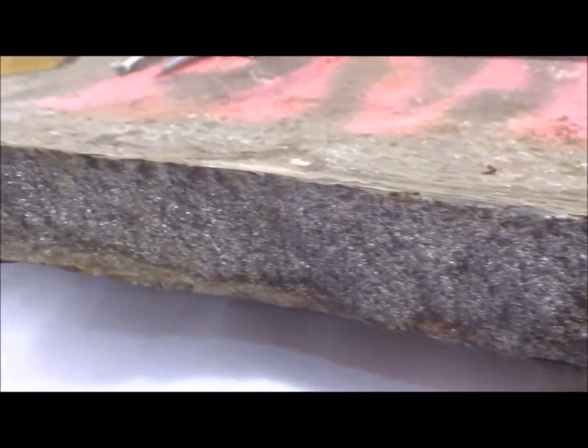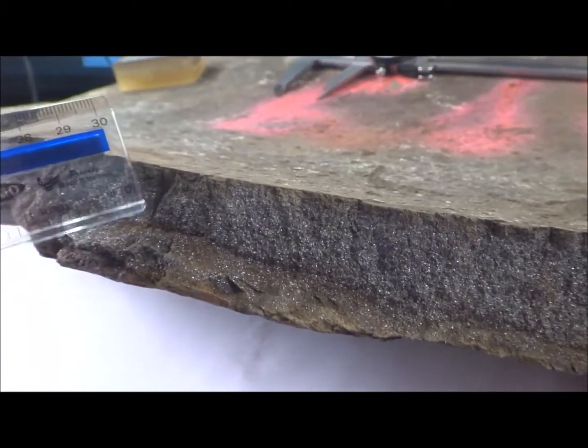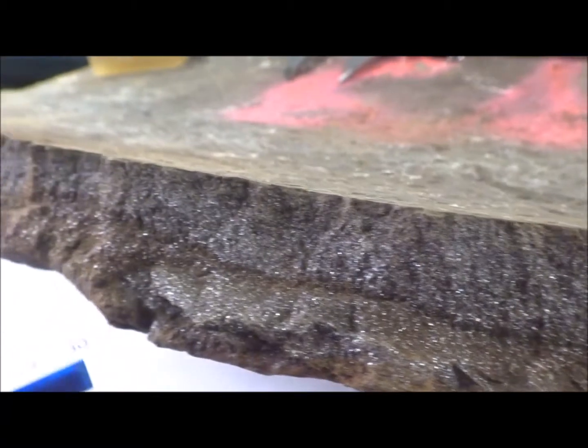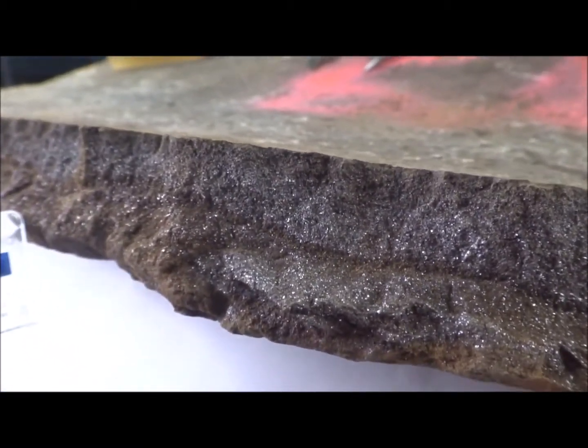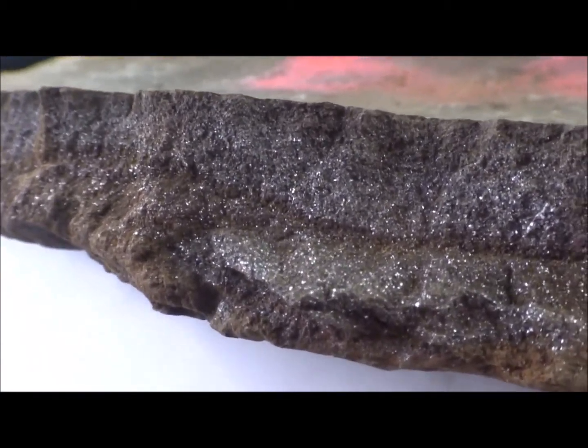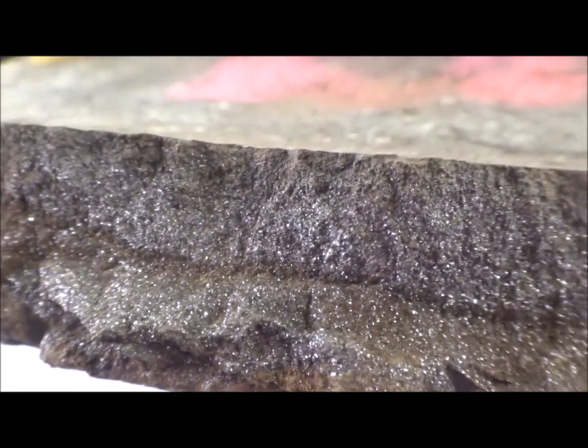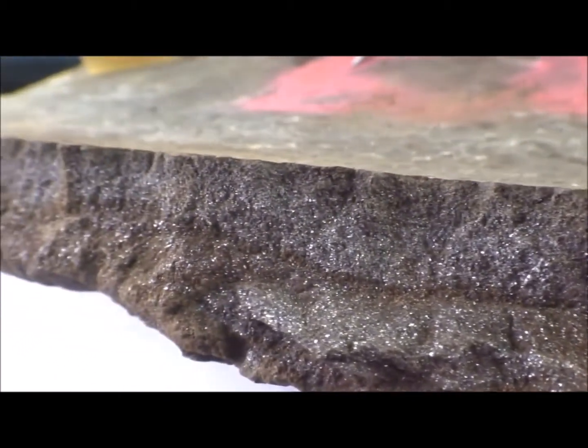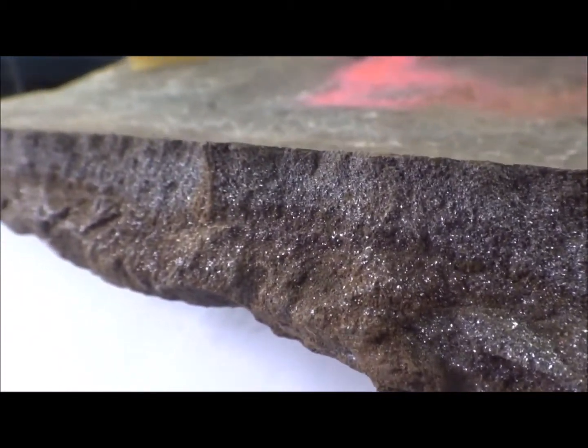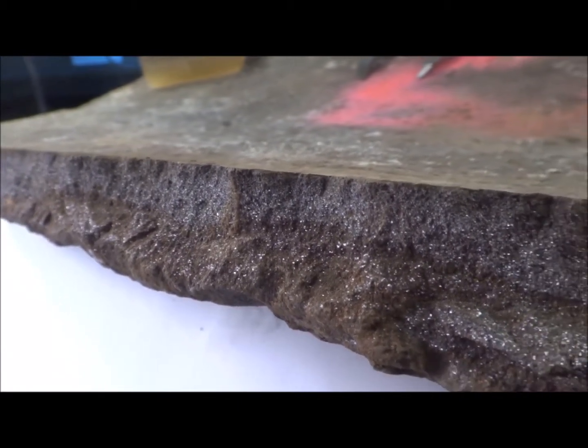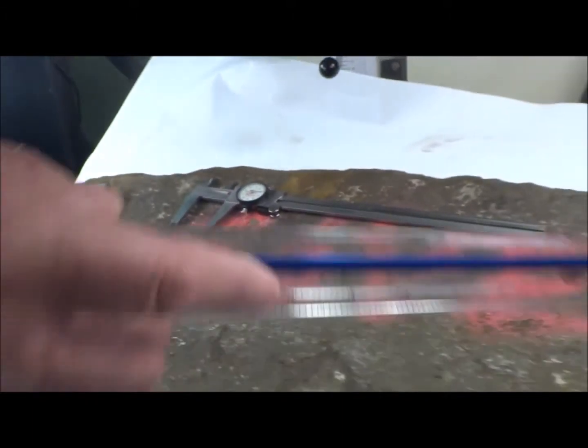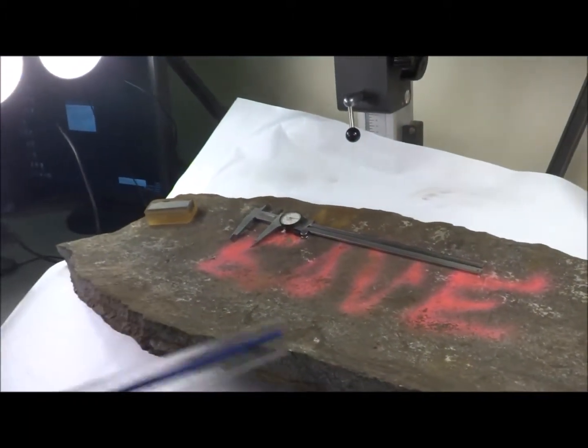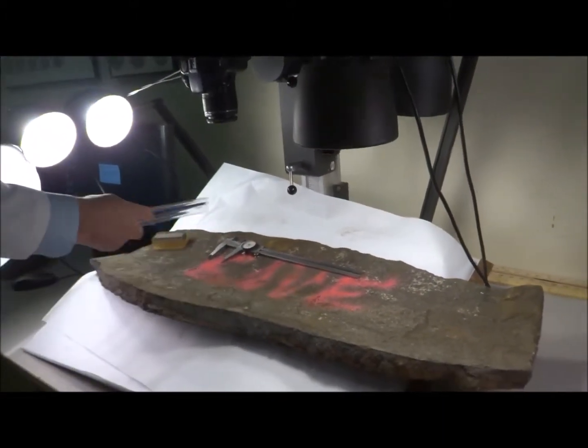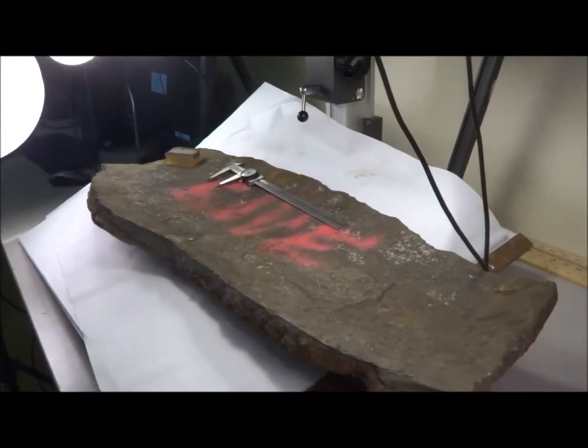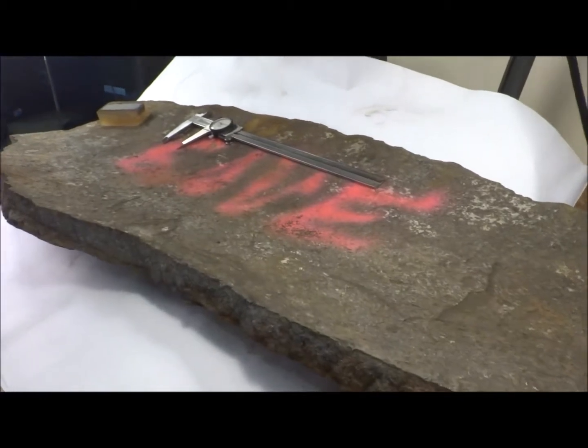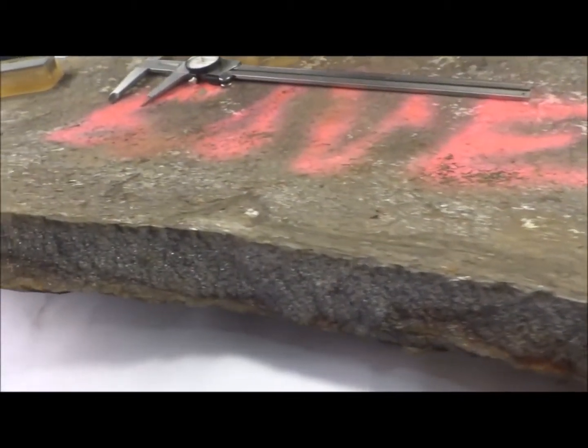The fracture surface is here, and you can see there's a difference in the structure between this light gray area on the inside diameter and a darker area on the outside diameter. The darker area represents graphitic corrosion. This is a corrosion process where the gray cast iron consists of graphite in an iron matrix. When corrosion occurs, the graphite flakes keep the iron corrosion products in place. Therefore, the pipe appears to be sound when looked at from the outside, but in fact the wall thickness is greatly reduced. This overall fracture is known as a window failure, when a large section of pipe comes out, releasing a large amount of water through this space. Other types of failure for cast iron could be transverse cracking, longitudinal cracking, or small diameter holes from corrosion. This is the most catastrophic form of failure for a cast iron pipe.